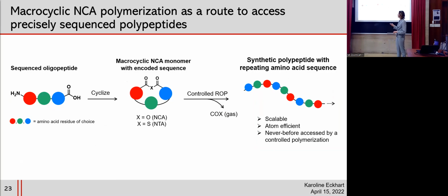So with this approach, we start with a sequenced oligopeptide, and then we cyclize that to form a macrocyclic NCA that's encoded with the amino acid sequence of the oligopeptide. And then we could polymerize that using a controlled ring opening polymerization to give a synthetic polypeptide with a repeating amino acid sequence. And because this is NCA-ROP, we expect this to be scalable and atom efficient, and critically would allow us to access repeating and alternating copolypeptide sequences through controlled polymerization for the first time.